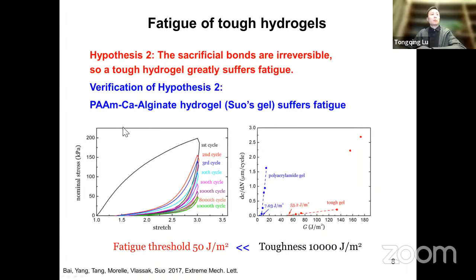The first paper to test the tough hydrogels is from Dr. Bai in 2017. They prepared this gel, and you can see the stress strain curve, loaded and unloaded, is a very large hysteresis, which means it suffers fatigue. And if you measure the fatigue threshold, the fatigue threshold of the tough hydrogels is about 50, so much smaller than its toughness. Yeah. So it's as we had predicted.